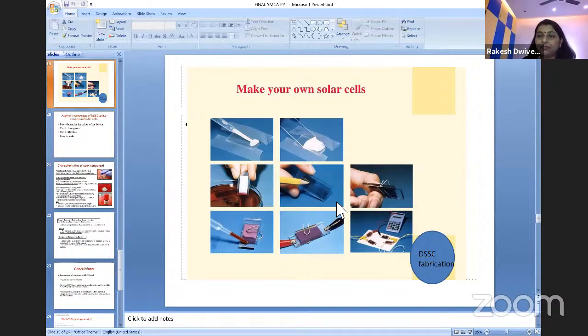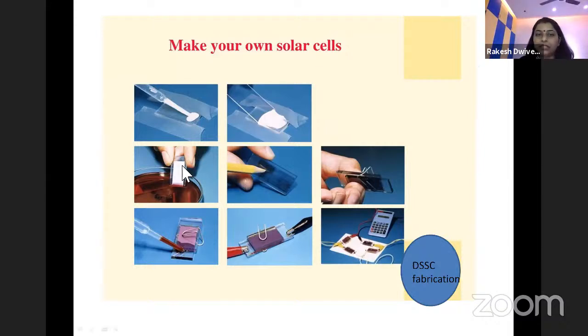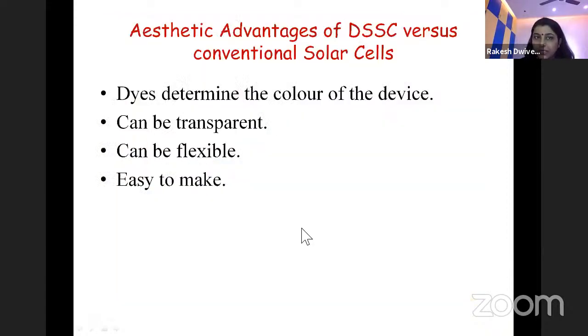If you see the fabrication of DSSC, it's quite easy. We just take the conducting glass, and initially we can fabricate this solar cell. On this conducting glass we deposit the TiO2 paste formulation, for which a specific method has to be used to make the paste. So we just deposit the TiO2 paste on this slide, and we dip this electrode in the dye, whichever dye we are using in our system.